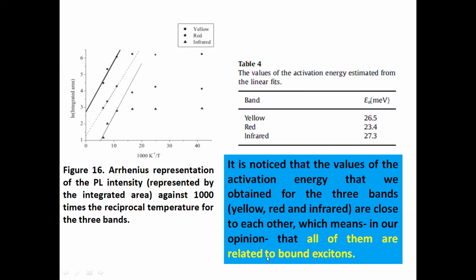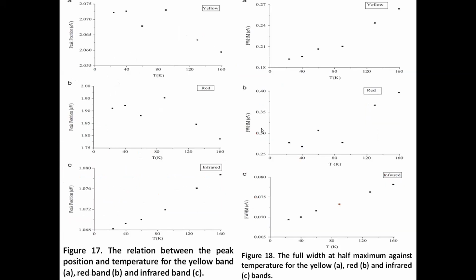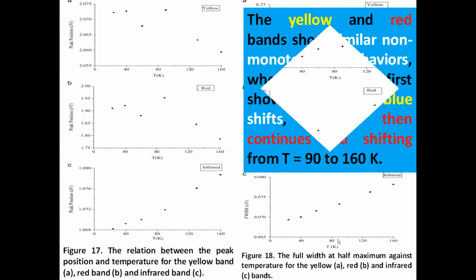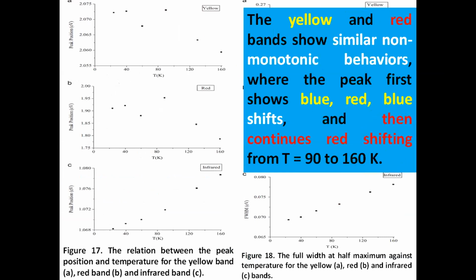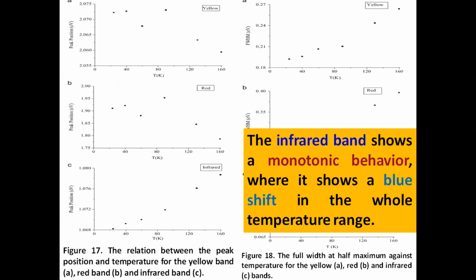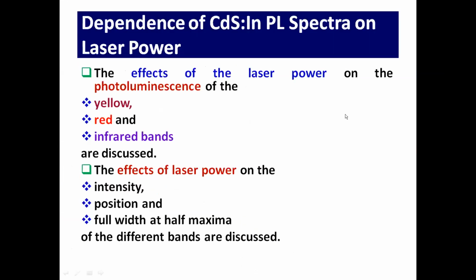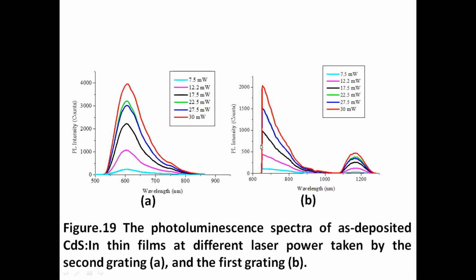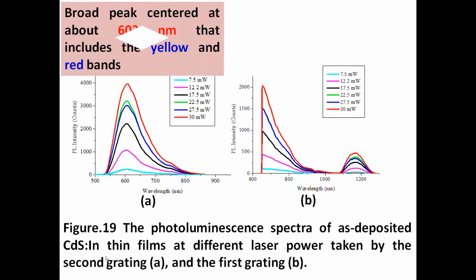Now here are the peak positions with temperature, as you see the relations, and the full width with temperature is also plotted. Now we come to the influence of laser power. Here are the PL spectra at different laser powers. As you see, the PL intensity increases with the laser power, and the asymmetry of the yellow-red band increases with laser power.